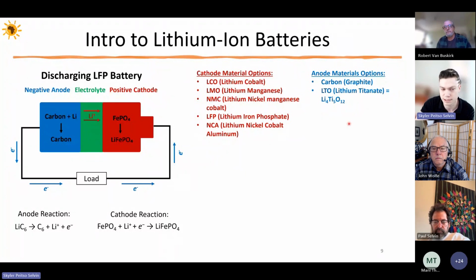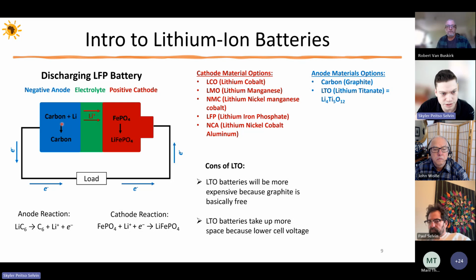Introducing lithium titanate into the anode increases the cost of the battery, and it also decreases the voltage of the battery. So this lends to the major cons of any LTO battery, and that's they will be more expensive because lithium titanate is more expensive than graphite, and they will be less energy dense because of the reduced voltage. So normal lithium ion batteries with a graphite anode will have around 4 volts terminal voltage. And when you introduce LTO, it reduces the electrochemical potential between the two materials, and the voltage of the battery will be reduced to around 2 volts. That therefore reduces the energy density of the battery by around a factor of 2.